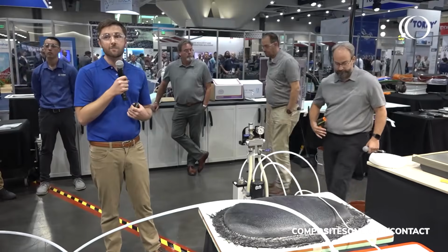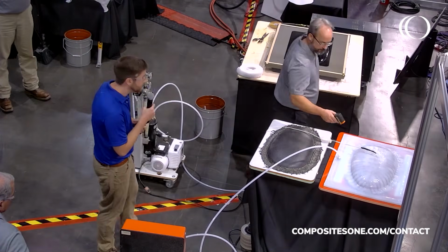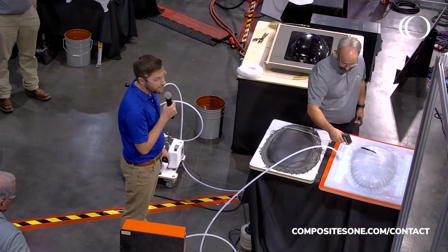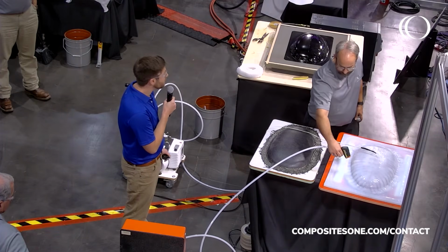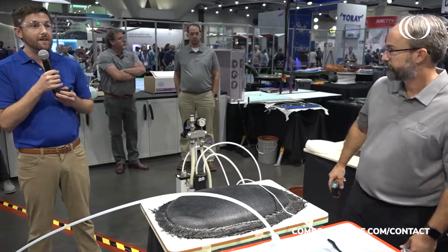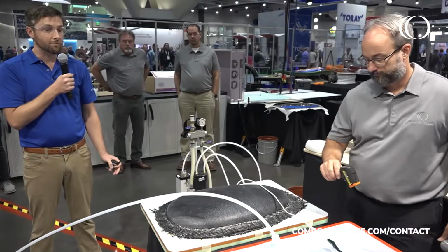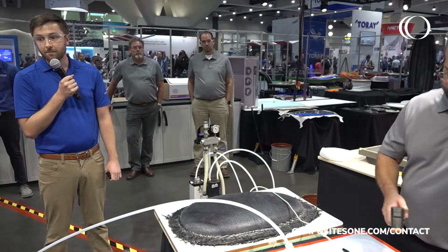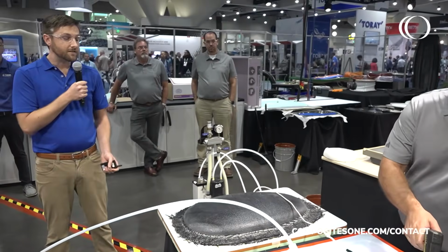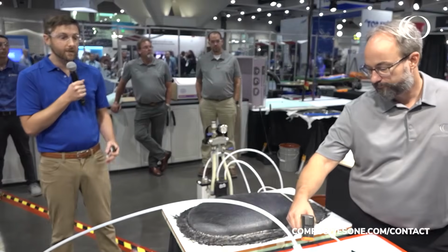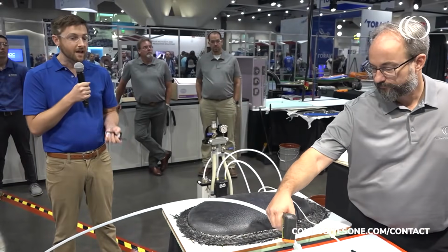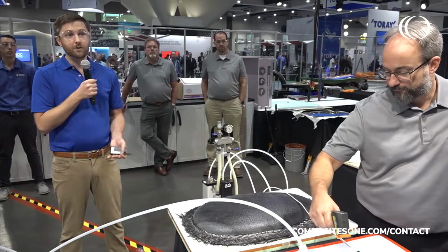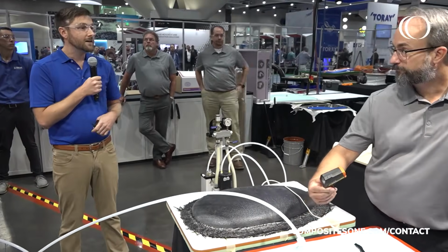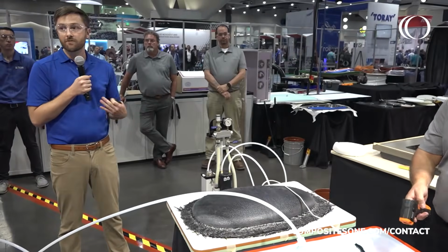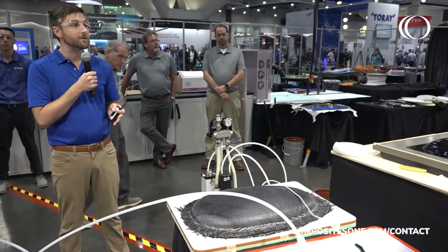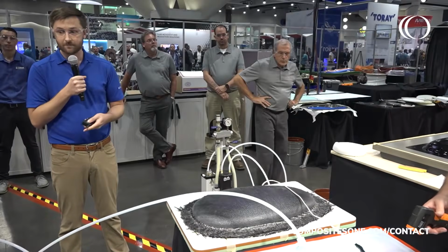Applied to our Qiso today is a powder binder. This powder is from Westlake. It's an 05390 uncatalyzed epoxy binder. The fact that it is uncatalyzed is great because you don't have to worry about outlife or keeping it cold. And then the fact that it's an epoxy chemistry means that it will still melt into your resin matrix after infusion. So it's used today as mainly a preforming tool, as James mentioned, so we can heat this binder at about 200 degrees Fahrenheit and tack multiple layers together, and also start to build shape in as well, to start preforming this fabric offline, which is great because it frees up your infusion tool to just do infusion, and we can make these preforms offline and transfer them onto the mold tool when you're ready to infuse.